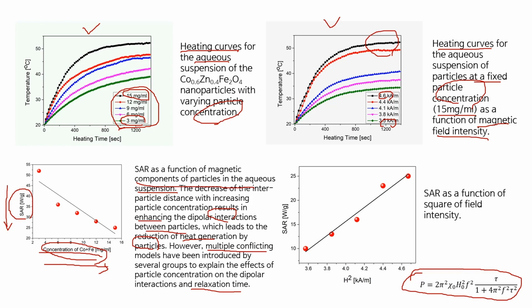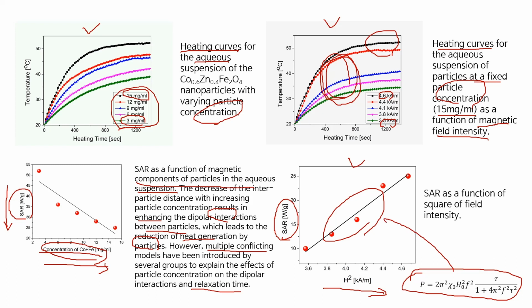So if we calculate using this data, SAR, we can calculate SAR using this data, and then this figure plots the SAR as a function of the square of the magnetic field intensity. We can see the linear relationship. So this linear relationship can be explained by this equation. So SAR is proportional to the square of the magnetic field intensity.